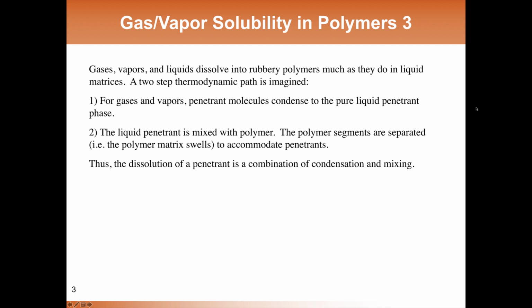There'll be an energy associated with each of these steps. So for the first step, the energy is the energy associated with condensation of the penetrant, and for the second, it's the energy associated with mixing of the penetrant with polymer segments. And in a preview of what we're going to see in just a moment, the energy associated with this first step is often vastly larger than that associated with the second step, and that has very practical consequences for gas and vapor solubility in polymers, which we'll go over in just a moment.